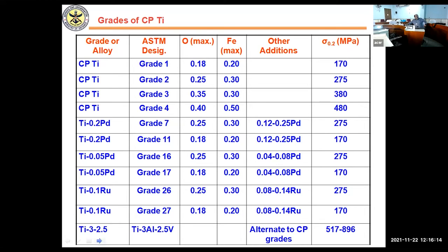And then there is this alpha alloy which I was talking about, titanium 3 aluminum 2.5 vanadium. This can be categorized as alpha alloys or alpha plus beta alloys, but normally because it is non-heat treatable and its strength is slightly higher. As soon as you alloy it with other elements, you can see the yield strength is higher. This is widely used in aircraft tubing.